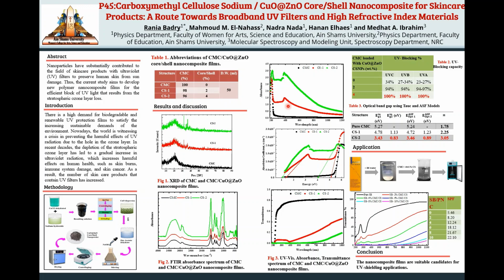the core shell nanoparticles. Also, we calculated the absorption coefficient and found that the absorption edge of pure CMC was shifted to the lower energy region with the addition of core shell nanoparticles, and confirmed the appearance of the second absorption edge. The transmittance spectra of pure CMC were found to decrease with increasing concentration of the core shell nanoparticles and extended to the visible region, which is a very good result.